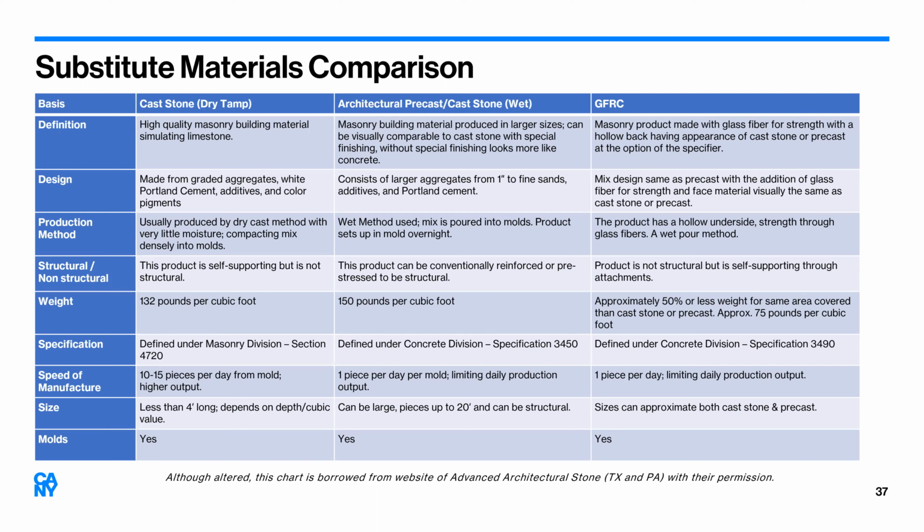We recently worked on a project where we replaced individual units of terracotta with precast. We isolated them not only because they're supported by their own steel structure, but also using neoprene pads, as well as a very specific mortar, which would take up compression if it ran into a situation where maybe there's a freeze-thaw cycle or something that puts it under a little stress. We have a lot of belts and suspenders to help us not damage that adjacent terracotta.